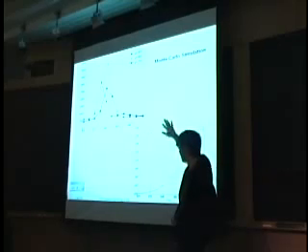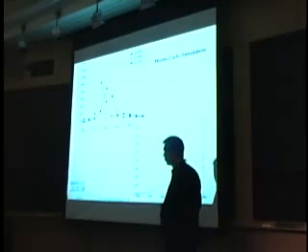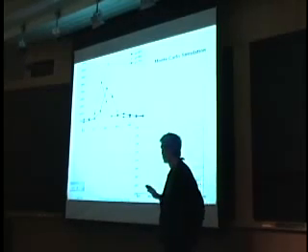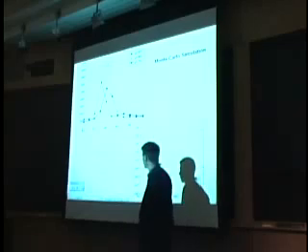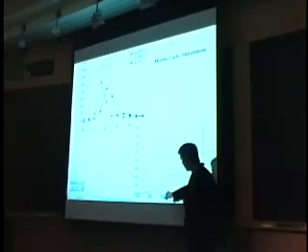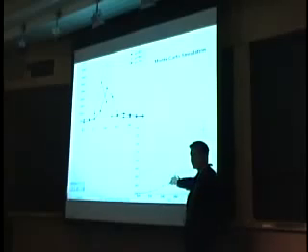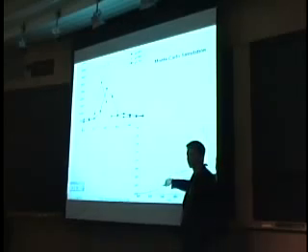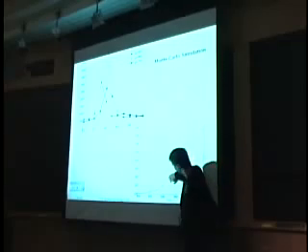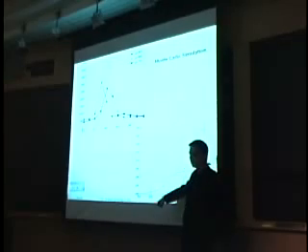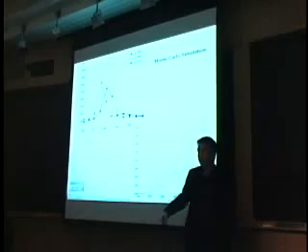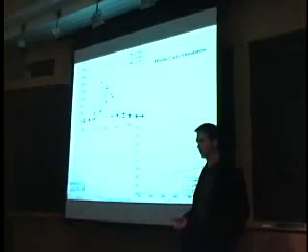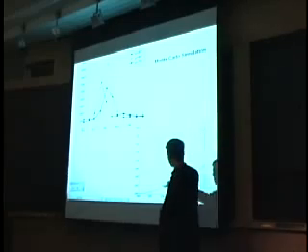The other peaks have slightly more points, but normally if you really wanted to know whether it's first or second order, you would refine it a lot more near the phase transition. Again, the energy seems to be continuous, but don't let the lines fool you. You've taken this point and that point and connected them, so of course they're continuous. But maybe this thing continues and then shoots down vertically, so it could still be first order. So you would normally refine this a lot more.